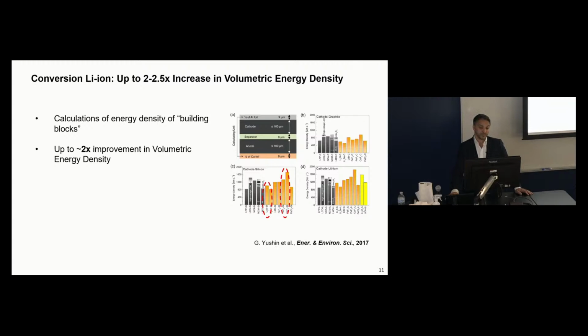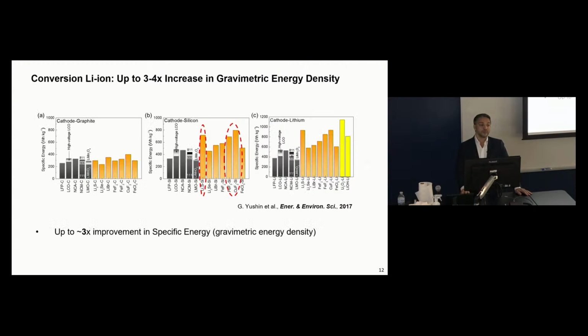You can make certain assumptions on the properties of these separator foils and electrodes, and you can estimate, depending on the composition of the cathode and anode, what kind of energy density, specific energy, or volumetric energy density you can get. And you can estimate that if you move to purely conversion-type chemistries, you can expect up to 2 times improvement in volumetric energy density and up to 3 times improvement in gravimetric energy density. Both volume and mass matter, because, as I mentioned, higher volumetric energy density gives you longer driving range in cars, right?